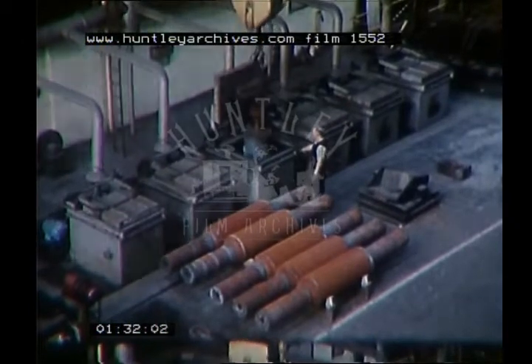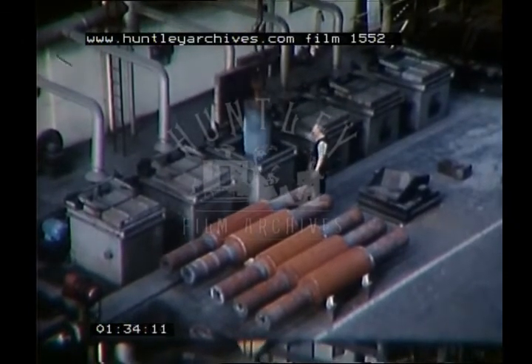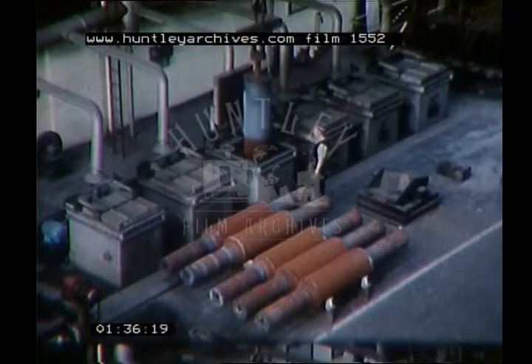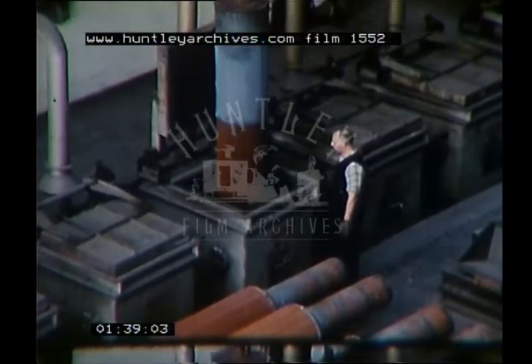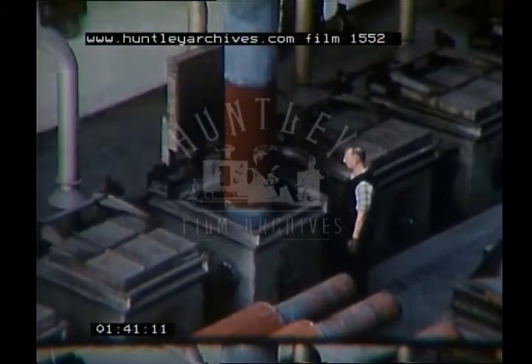After hardening, rolls are tempered to establish the surface hardness appropriate to service requirements. Tempering consists of reheating the hardened steel to a temperature usually in the range of 100 to 200 degrees centigrade.